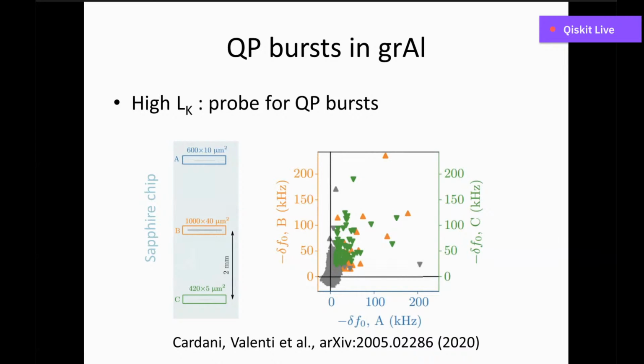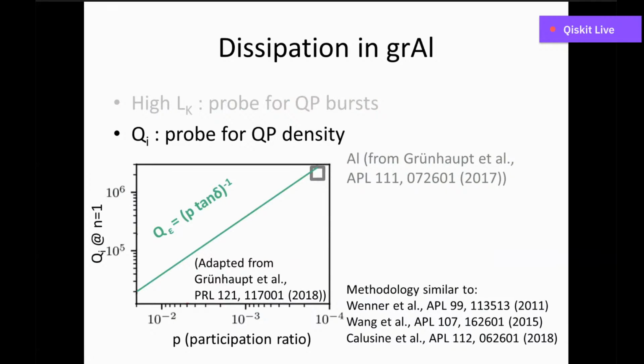Another tool or property of granular aluminum that makes it useful to probe for the effect of radioactivity is dissipation. Because the internal quality factor of the granular aluminum resonators that we made is dominated by quasiparticles. I will convince you of this by showing that the dissipation is not dominated by the other usual suspect when it comes to superconducting losses, which is dielectric losses.